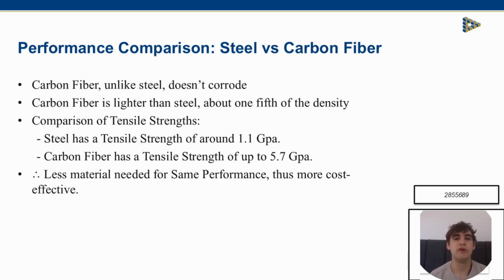To understand why carbon fiber is a strong alternative to steel reinforcement, we need to compare their performances. Steel needs to be encased to prolong the time before corrosion sets in, and also needs more concrete to support its weight. On the other hand, carbon fiber doesn't corrode, is a fifth as dense, and has a tensile strength of around 5.7 gigapascals, over 5 times that of steel's 1.1 gigapascals. This allows for lighter designs using less material overall.